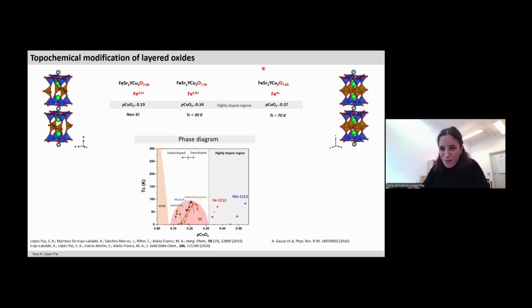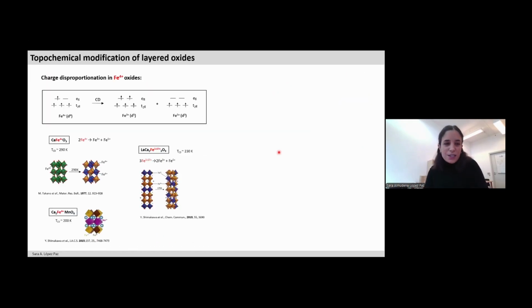because I'm sure that some people on my floor would ask me about this iron 4+, and it is indeed a not very usual oxidation state for iron, and it is actually not very stable, because if we assume this oxidation state for iron in an octahedral crystal field, we'll actually have some electronic degeneracy that the system will like to release. So one way that the system has to lift this degeneracy is to undergo a charge disproportionation process and be present instead as a mixture of iron 3+ and iron 5+.